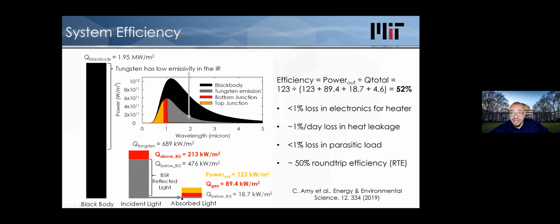That reflector is not perfect. So if there's a couple percent absorption, you get some heat absorption for the below band gap light. Up here, we can convert those photons pretty efficiently, but not perfectly. So you still get a bunch of heat generation for the current flowing in the cell because you've got some inefficiency in the quantum efficiency. You've also got voltage loss. All these things accounted for, you end up with about 123 kilowatts per square meter of power output. You end up with these other losses.